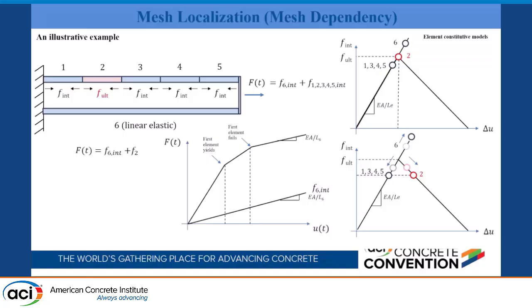So what is the overall effect of this? Let's just monitor what's happening to F of t versus the overall displacement that is experienced on the right-hand side. We're going to have a composite stiffness that you can see in the upper curve, and that composite stiffness will change when the first element yields. Let's say that's F2 in this case. And then it is going to be a reduced stiffness because now effectively element 2 is contributing less to that stiffness. And it is going to continue on until element number 2 drops into the failure regime and completely breaks off, at which point all of the loads will be carried by the member in the bottom, F6. So the slope of that curve, the backbone curve, will converge to identically the stiffness of member 6.